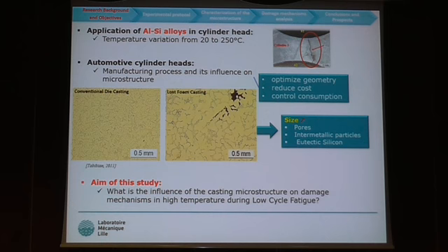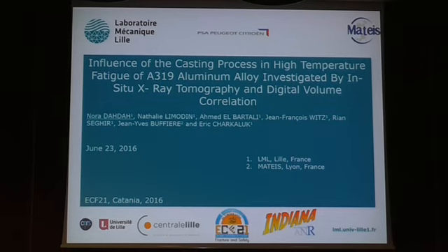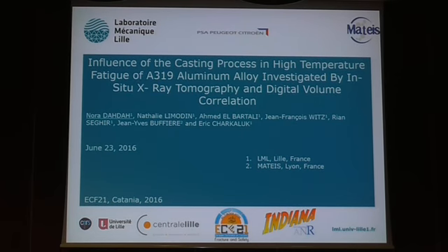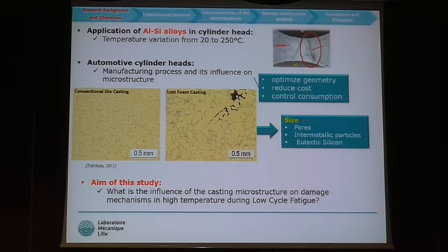This study is about aluminium silicon alloys used in cylinder heads. The cylinder head is submitted to several thermomechanical stresses. Indeed, during the start-stop of the vehicle, the temperature is from 20 to 250 degrees, which leads to the crack in the fire zone of the cylinder head.